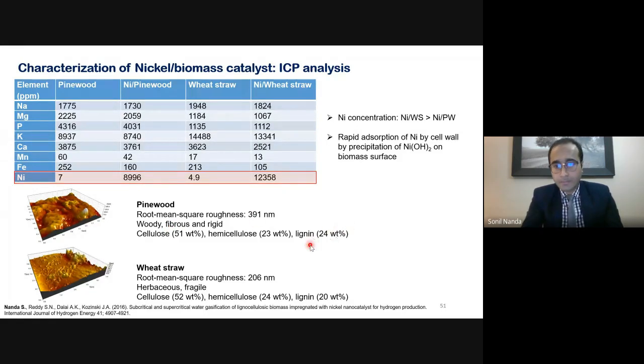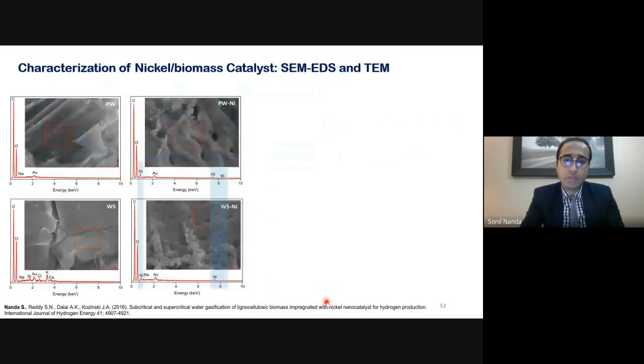That's what we determined. Now, because of the presence of lignin, and if you recall in some of the earlier slides where I mentioned that lignin acts as a barrier between the external environment and the internal plasma of the cell, the presence of more lignin in the pine wood acted as a barrier preventing the adsorption of nickel from the solution into the pine wood cell. But wheat straw, since it had relatively less lignin content, adsorbed more nickel.